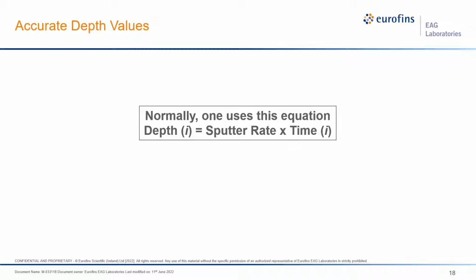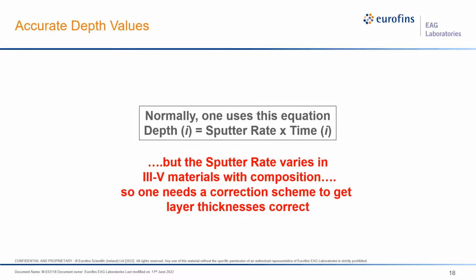But not only must we get the elemental concentrations correct, but we also must get the layer thicknesses correct. There is a large change in composition between layers, and this complicates matters. As shown in this slide, we normally determine the depth of each data point by multiplying the sputter time of each data point by the sputtering rate. One normally determines the sputtering rate by measuring the depth of the sputtered crater and dividing by the total sputtering time. However, the sputtering rate varies in III-V materials with composition, so one needs a correction scheme to get the layer thicknesses correct. And the next slide just shows just how significant this sputter rate change is.